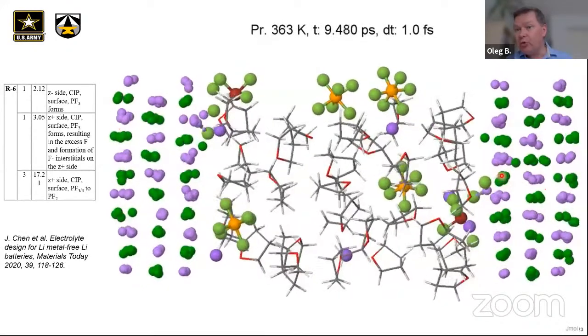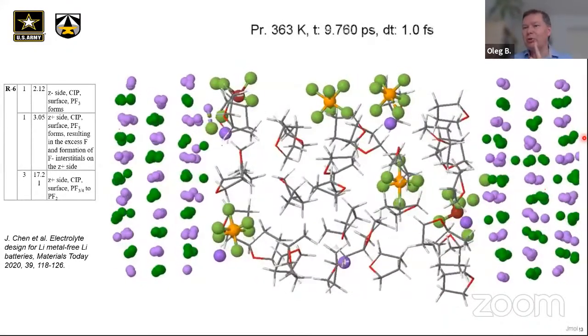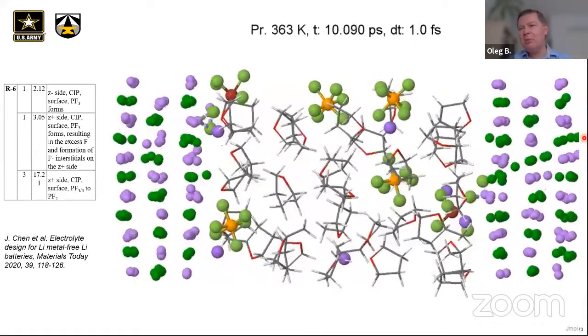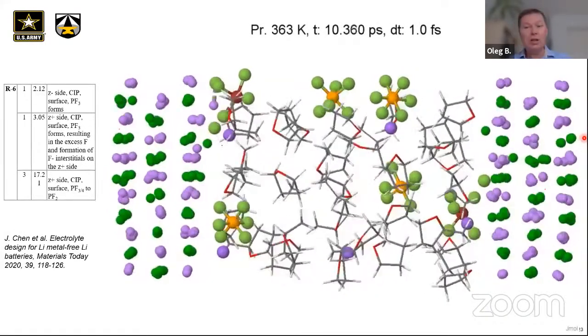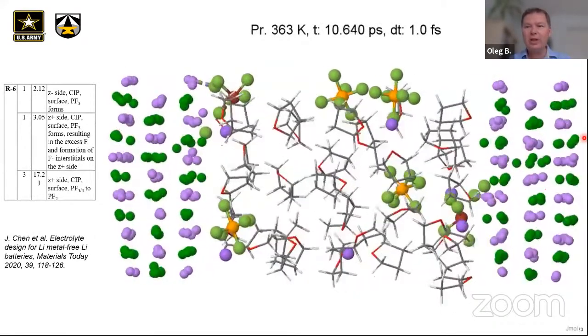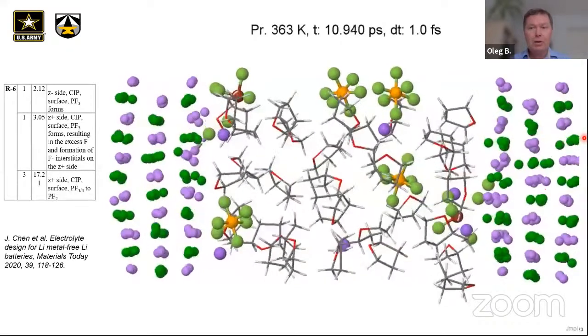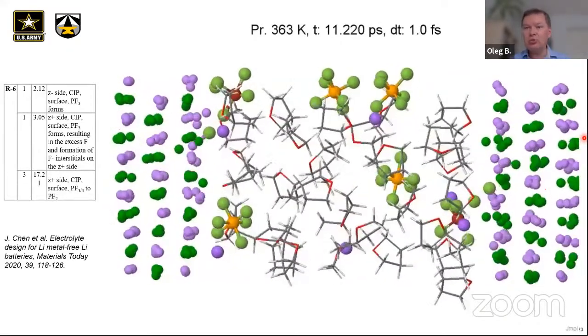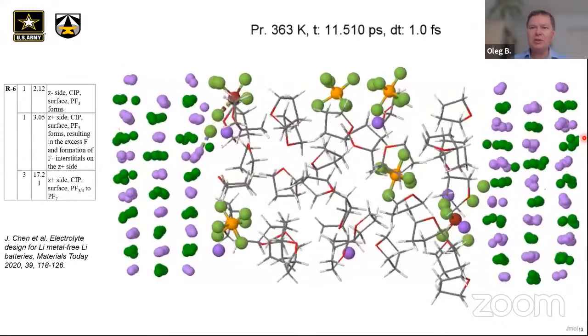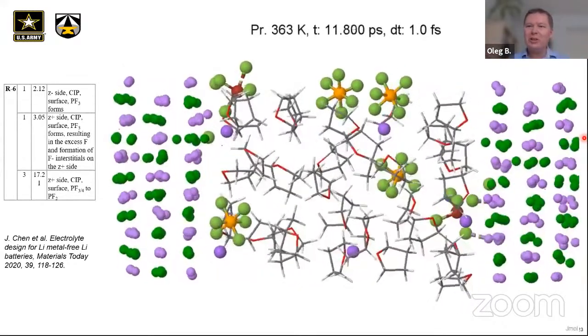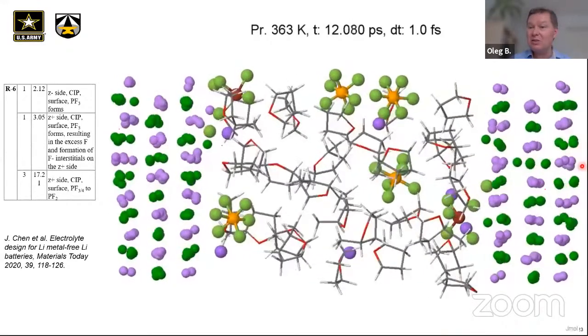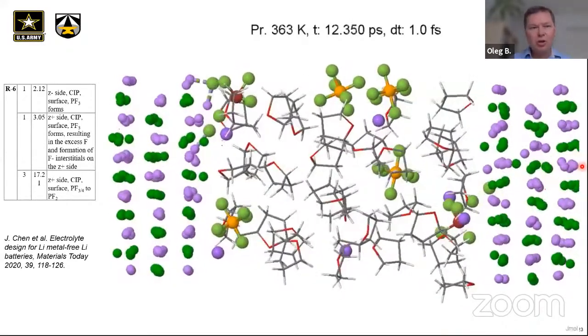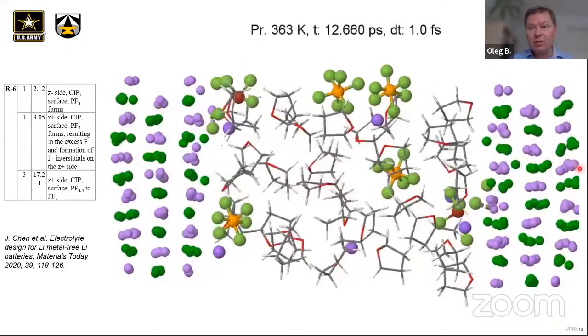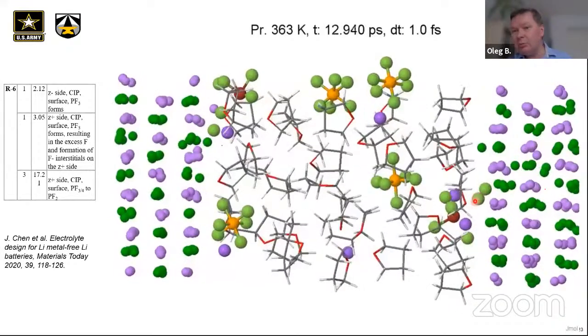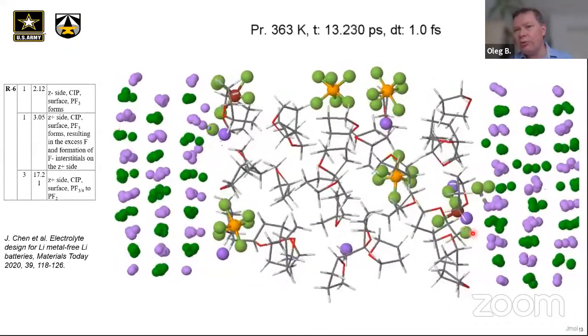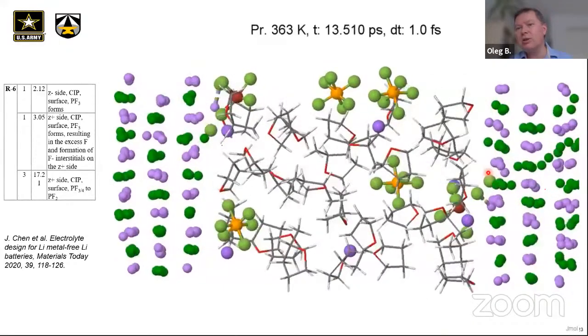So this type of fluorine transfer and creating LiF on the other side might be something which is unique to the nanoscale aspect of the LiF-based SEI. Because what really matters is not what diffused, but the relative diffusion of the lithium to the fluorine. So if fluorine moved and readjusted this SEI next to the lithium metal, that's already motion of the lithium to the other side. So why did it happen? Because locally, when PF6 gives out all 3 fluorines, there is an excess fluorine concentration.